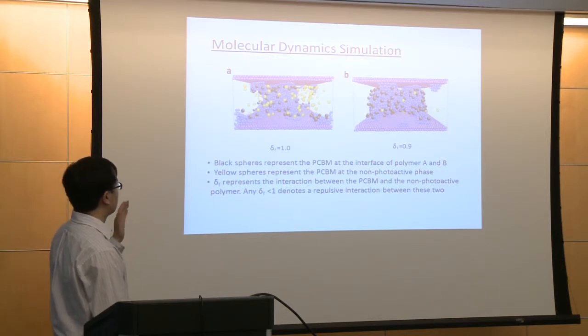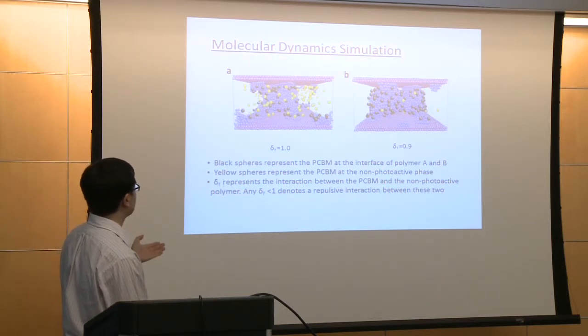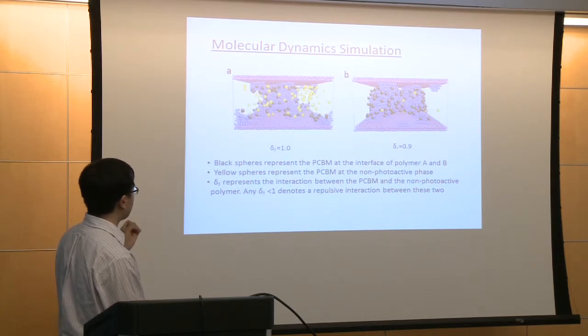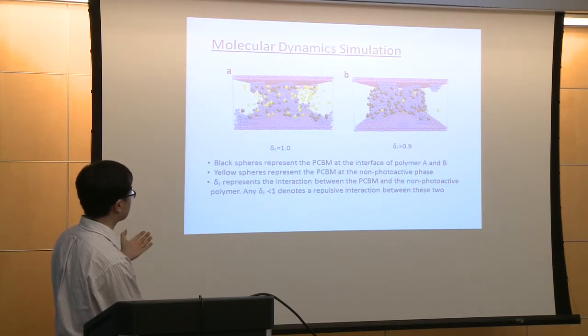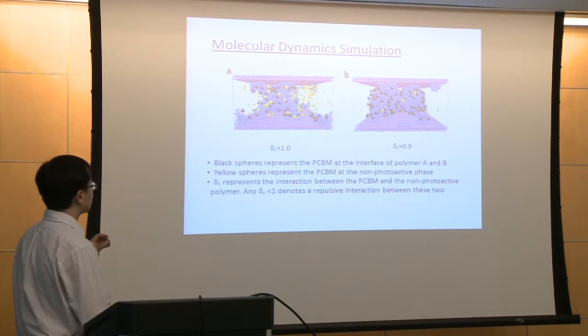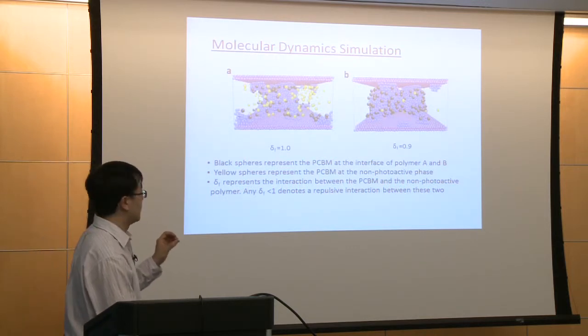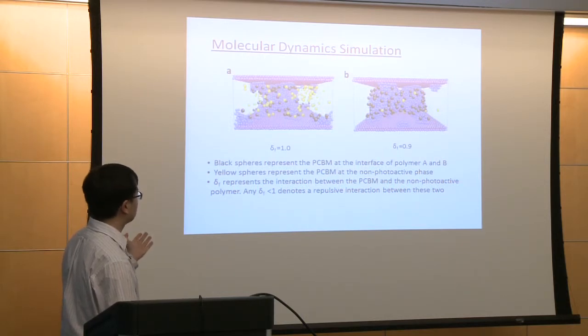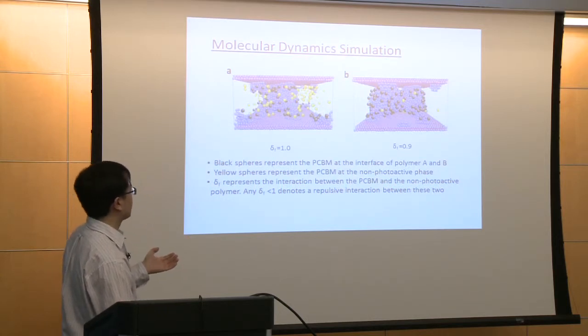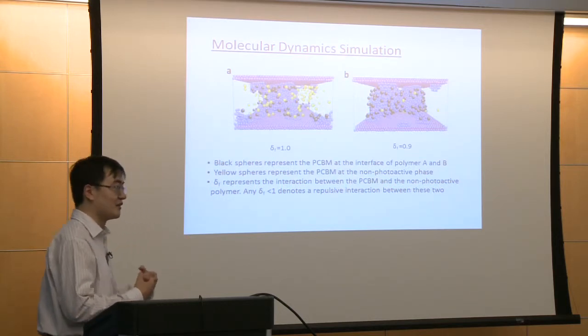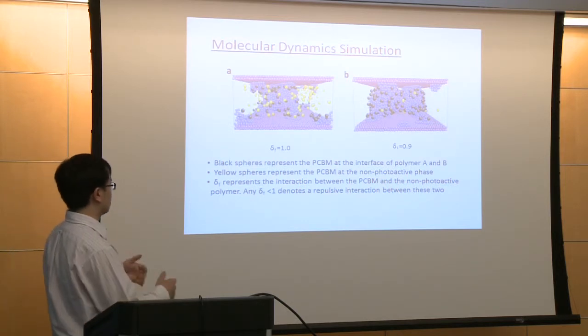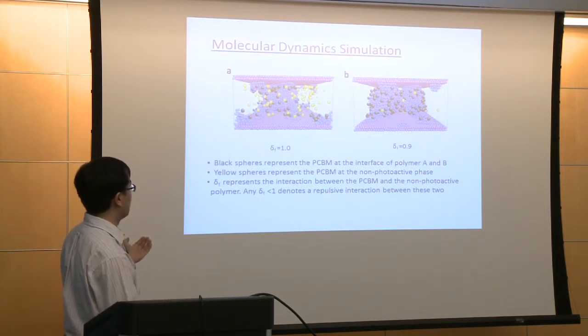Okay, so here the yellow spheres represent the PCBM in the second polymer phase, and the black spheres represent the PCBM at the interface. So when the delta F is equal to 1, what does that mean? It means there's no interaction between the PCBM and the other polymer. They peacefully stay together. Okay, so in this case, you can see almost half of the PCBM will be located in the secondary polymer phase, and half of the PCBM will stay at the interface between the 2 polymers.